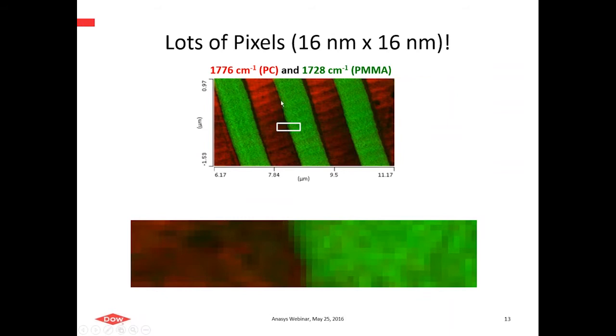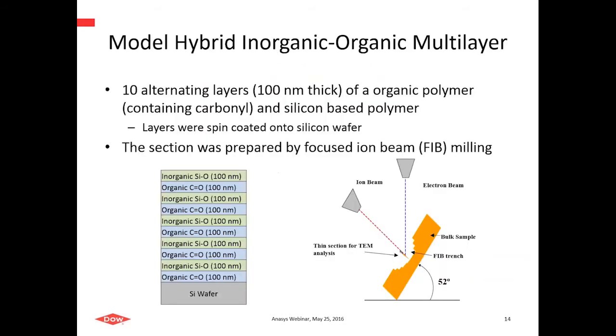If you look a little bit more closely, we can blow up one of these pseudocolored maps and look at the pixel count at the edge, and in fact, it is about 4 pixels from low intensity to high intensity across the edge, which puts us clearly in the nanoscale regime for measurement. So that example, that's actually something that would be tractable by doing confocal Raman, albeit with many fewer pixels in each of those 2 polymer layers.